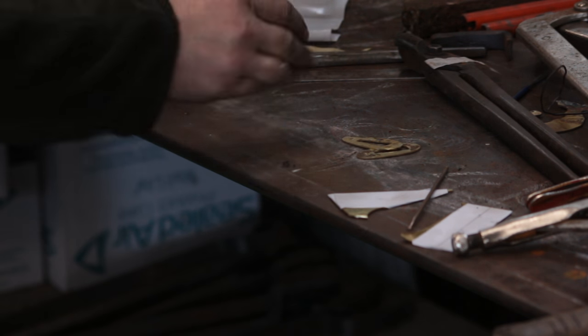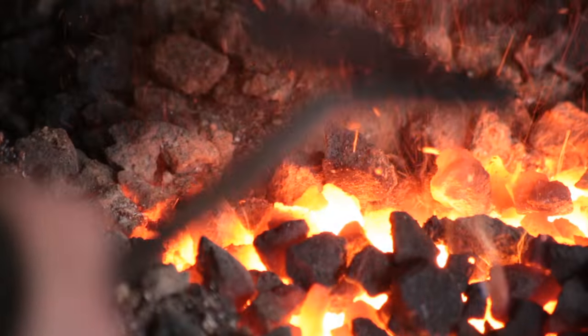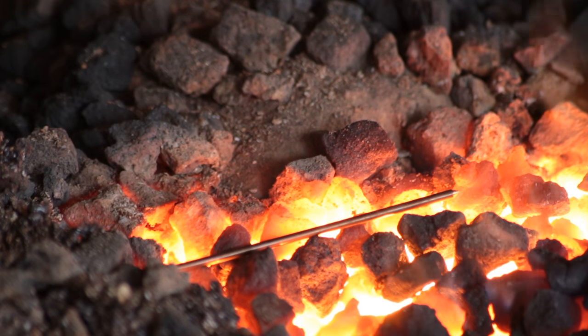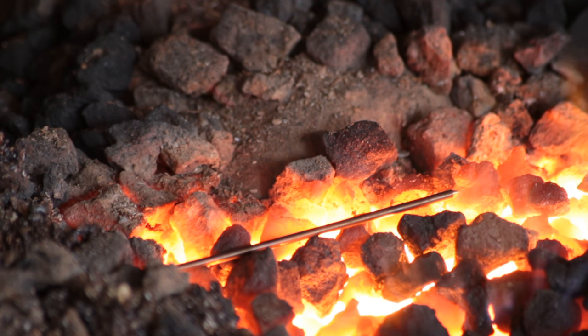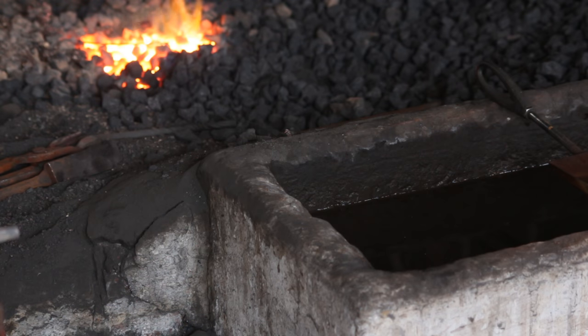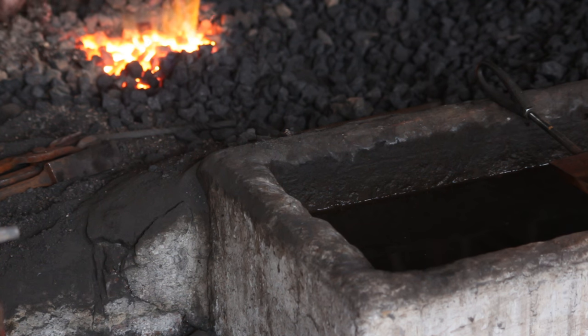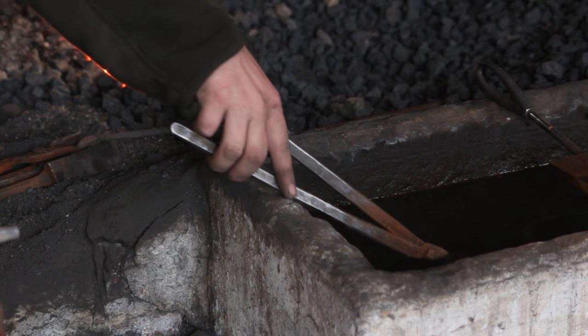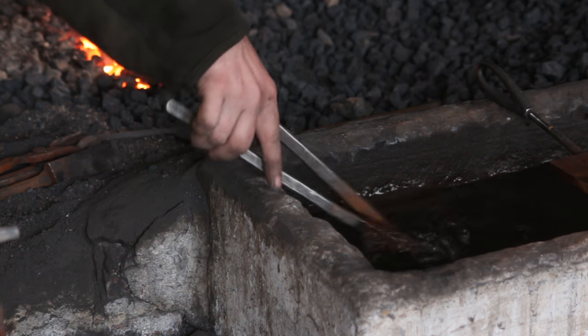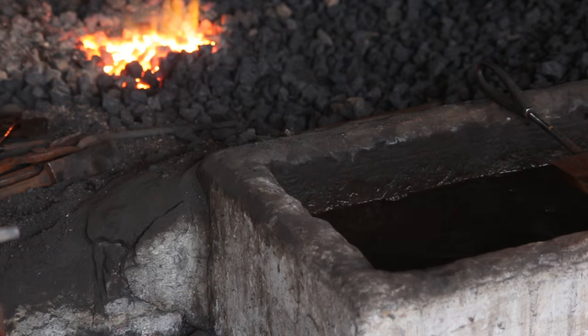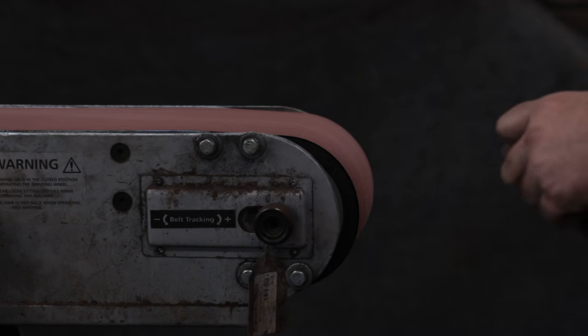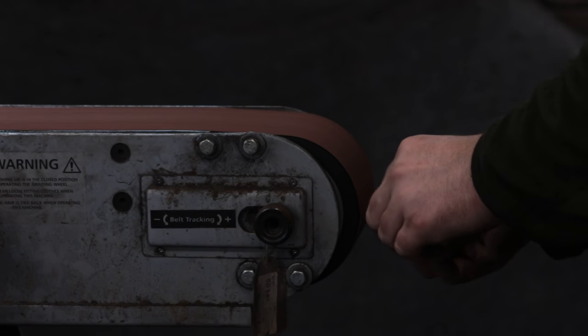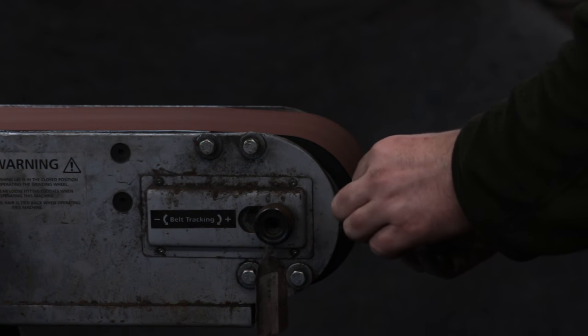And at this stage I have a piece of brazing rod which I will just anneal on the fire. So with brass to anneal just get it up to a red heat, a dull red heat, careful not to melt it and quench it off. Brass is different from ferrous metals because you will actually quench it to anneal it. So I'll also knock off the end just to make it slip through the hole better.